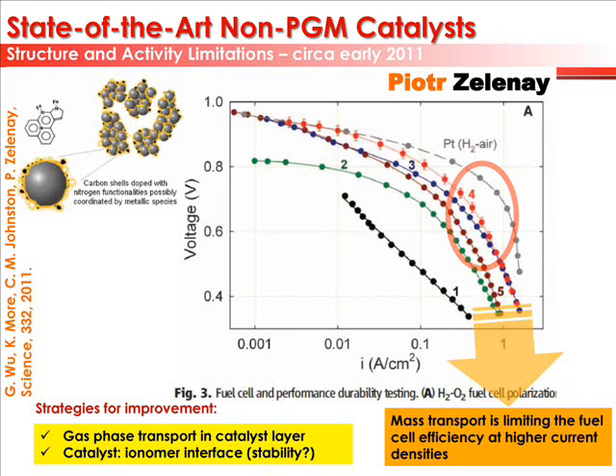So everybody and his mother today makes catalysts by pyrolyzing things that have nitrogen and carbon and obtains something that is really good. Two or three groups can make catalysts that are really good in oxygen reduction. But then when it comes to actually meeting the industry standards, they all do that by extrapolation. And they do it by extrapolation because the structure of their catalyst does not allow transport. The transport limitations start quite early. They are not starting when they tell you, when they are dominating.